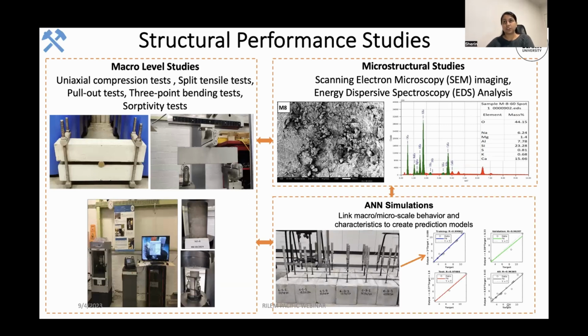So in the bottom picture, you can see that there is a pull-out test setup, which is mainly conducted to assess the strength between the basalt FRP bar and the self-compacting geopolymer concrete. We have also done modeling using artificial neural network to see how it performs for any combination of different parameters of the particular self-compacting geopolymer concrete when reinforced with BFRP.